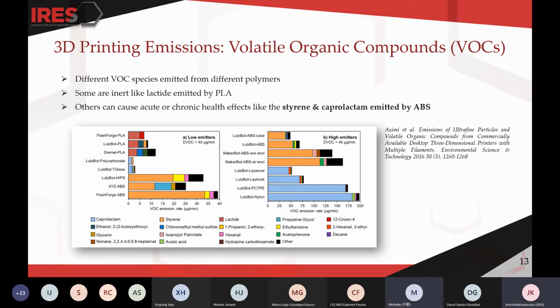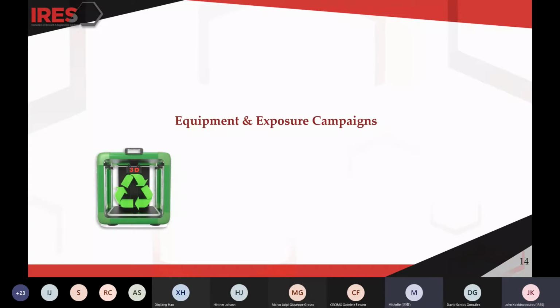Now concerning VOCs, several volatile organic compound species can be emitted depending on the composition of the filament that is used. For some filaments, the emitted VOC species do not present a risk, as is the case for lactide, as you can see from the chart, which is emitted from most PLA filaments. However, many of them, like styrene and caprolactam, which are emitted from ABS filaments, can result in acute or chronic adverse health effects. In the following slides, we are going to describe the equipment and methodology we use in order to measure ultrafine particles and volatile organic compounds.